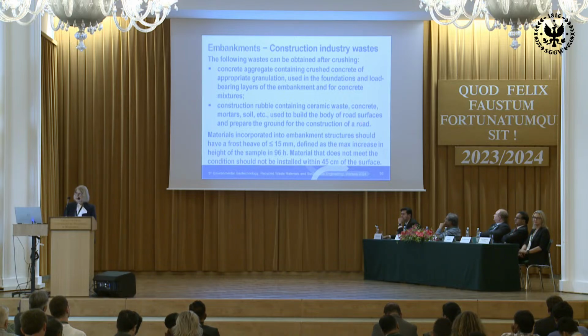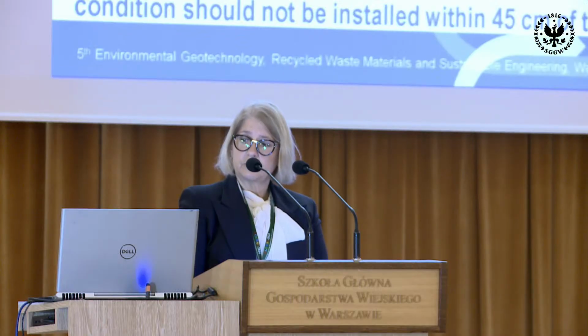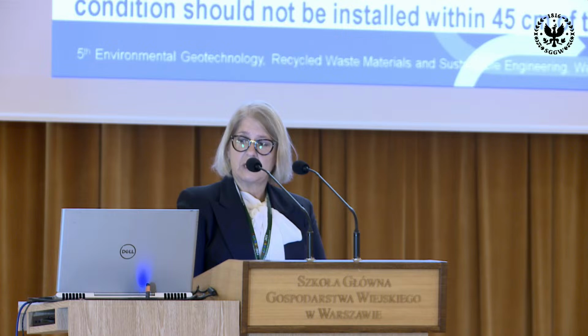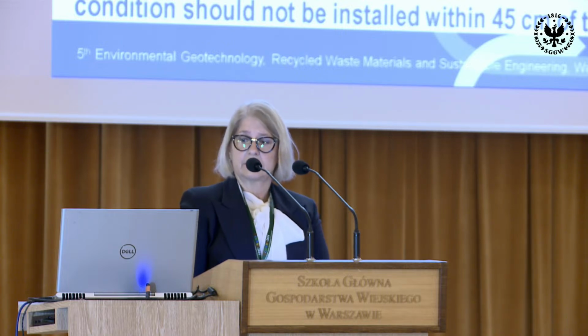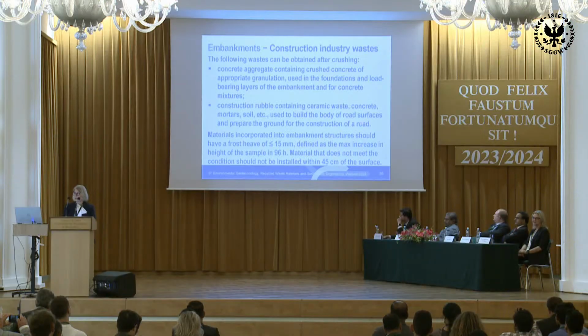Materials incorporated into embankment structure should have a frost heave lower than 15 millimeters, defined as the maximum increase in height of the sample in 96 hours. Material that does not meet the condition should not be installed within 45 centimeters of the surface.